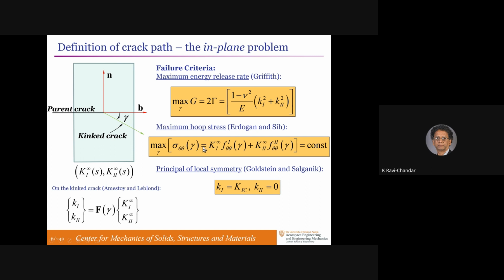In a brittle material, the crack wants to grow in the direction where there is no shear, or where the tensile stress is maximum. So the stress intensity factor in mode 2 on the kinked crack is 0, and the stress intensity factor in mode 1 on the kinked crack is equal to the fracture toughness of the material. All of these criteria are very close to each other. Experiments are not able to distinguish between one and the other. And so you could use any one of them and they'll predict what goes on.